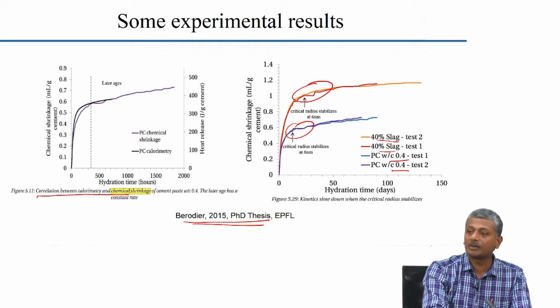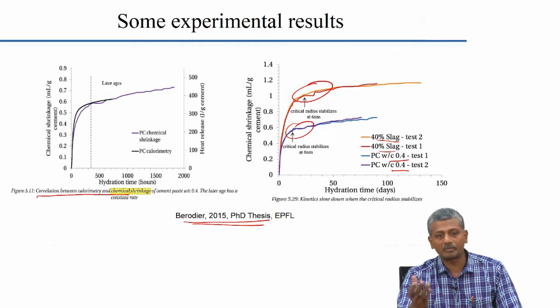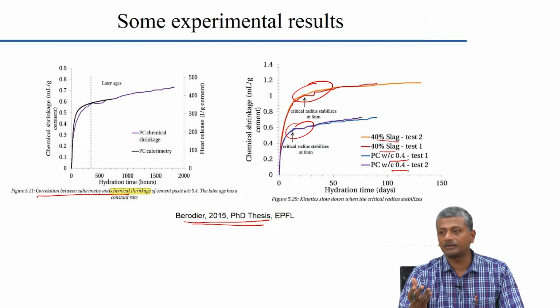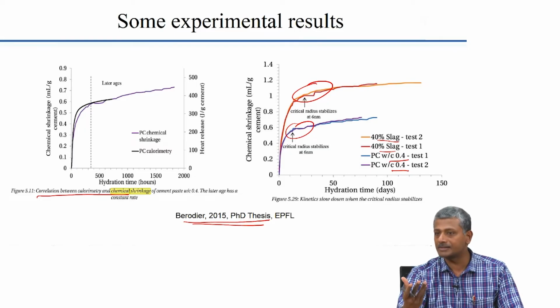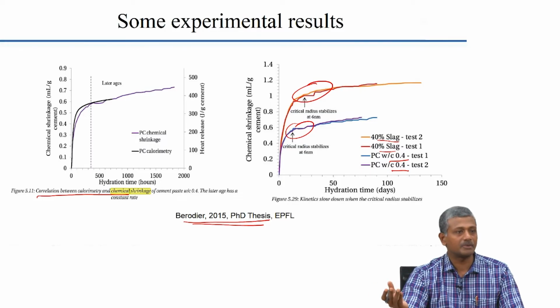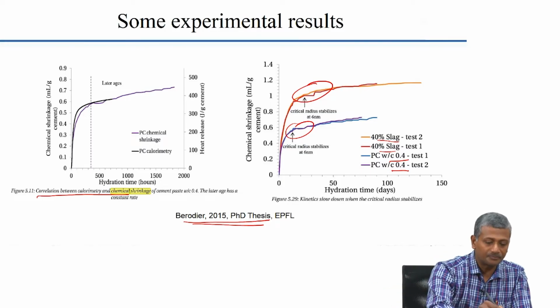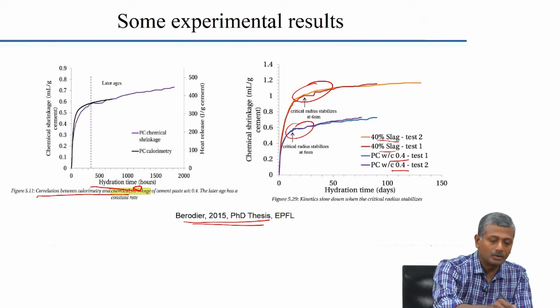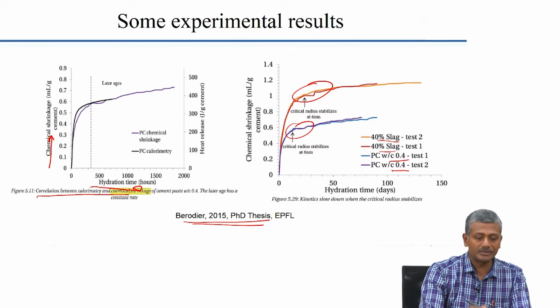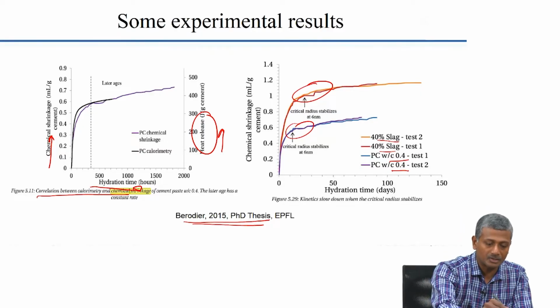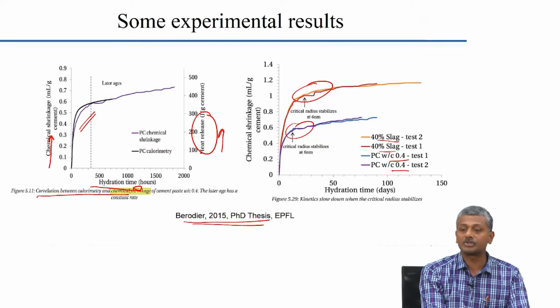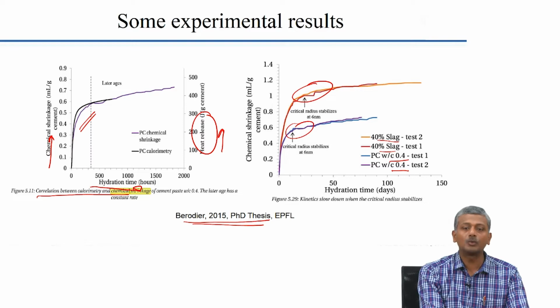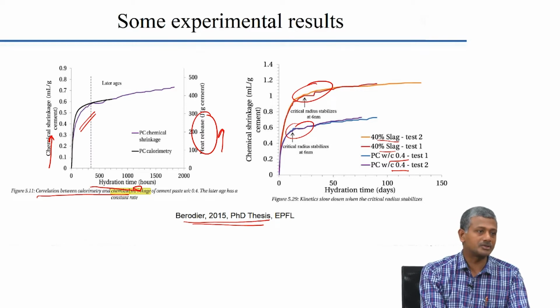Okay. So, then there is also correlation between calorimetry and chemical shrinkage. Calorimetry implies the study of the heat evolution pattern, and the total heat that is evolved is also proportional to the amount of hydration that is happening in the system, right. So, as the hydration time increases, your chemical shrinkage also increases and the overall heat release also increases. You can see that the correspondence between heat release and chemical shrinkage is fairly good. You see almost a 1-to-1 correspondence between chemical shrinkage and the heat release.